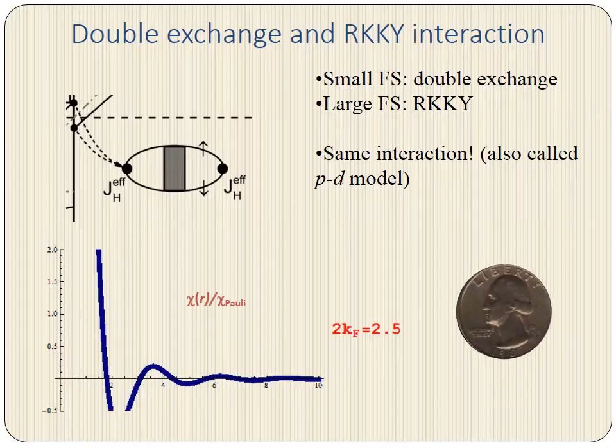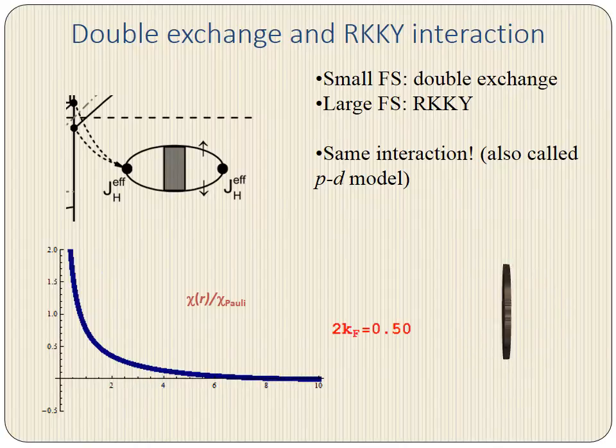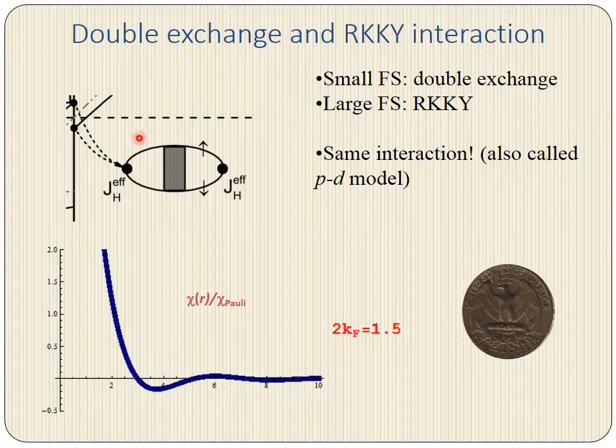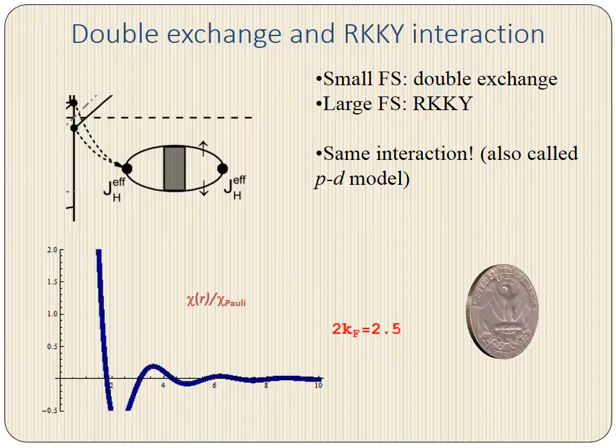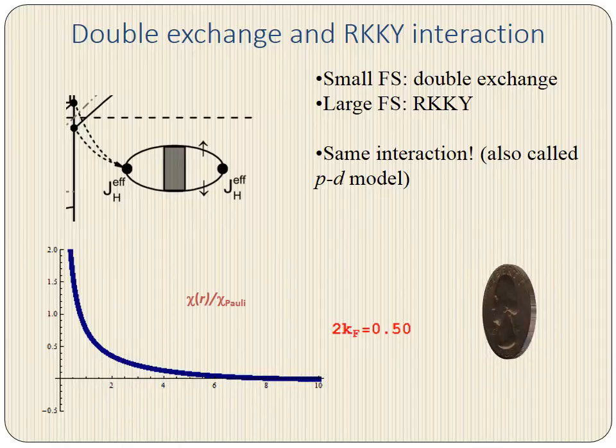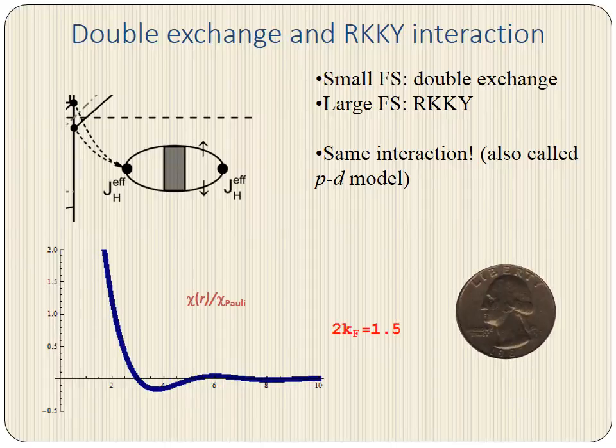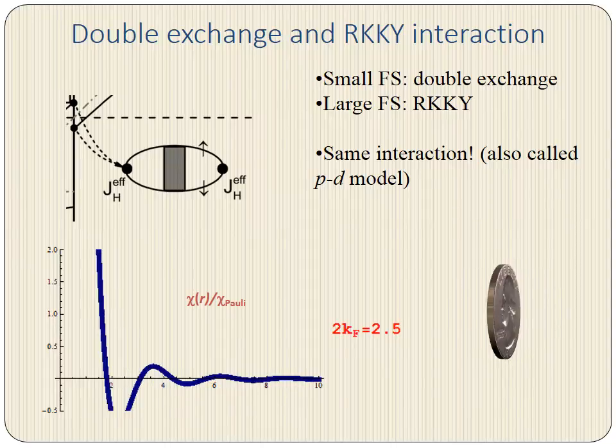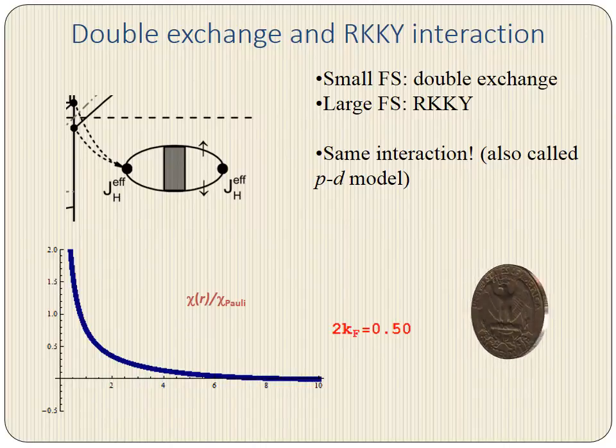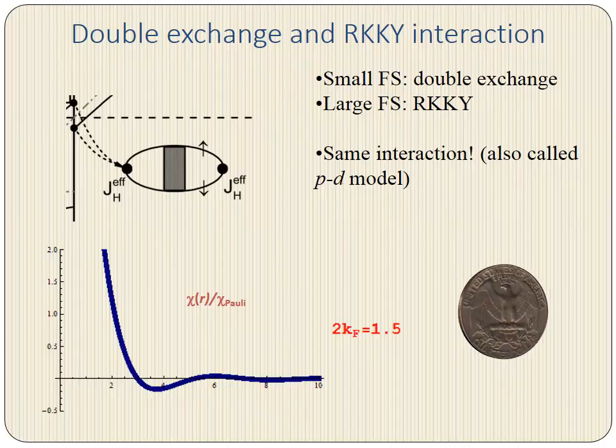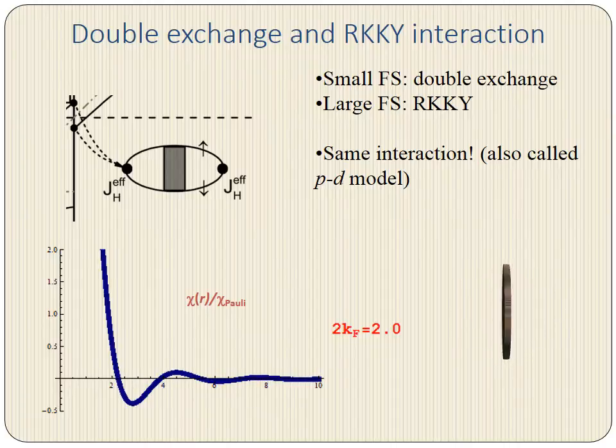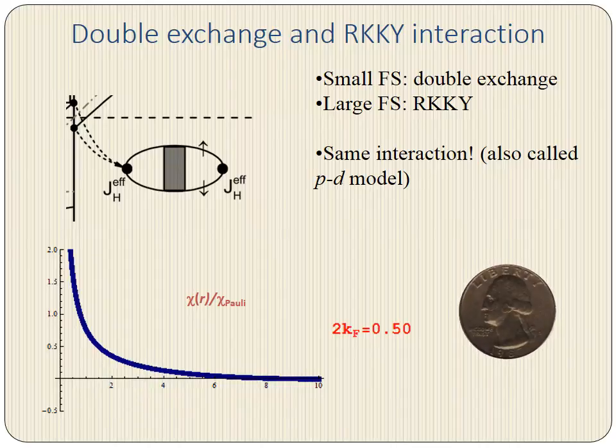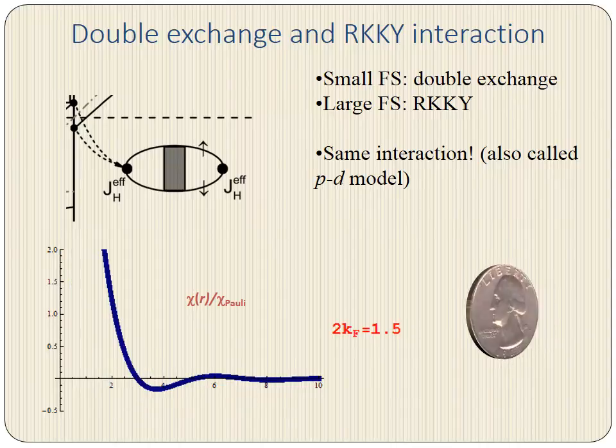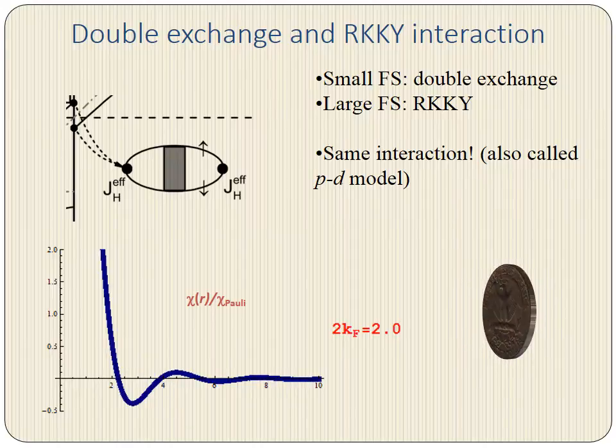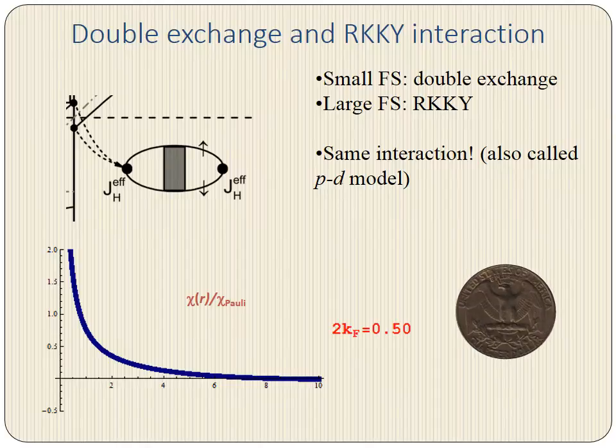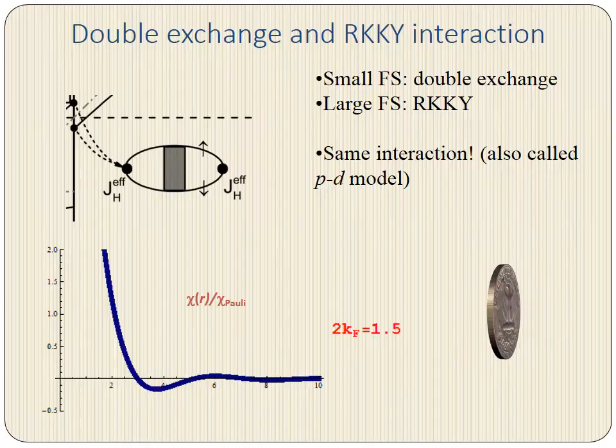This might seem like a bit of a pedagogical tangent, but it is an important point to drive home, as the dilute magnetic semiconductor literature has used different terminology to describe the physics of this polarization diagram. When we're in the small Fermi surface limit, in the literature it's usually been identified as the Zener or PD model, and has been discussed as being fundamentally different from double exchange. The main point of contention is whether double exchange, by definition, requires the existence of either an impurity band at the Fermi level or non-equivalent charge sites on manganese. Our broader view is that it's all the same thing. The details are contained within the vertices, and since the whole thing is squared in the end, you formally get the same effective interaction.